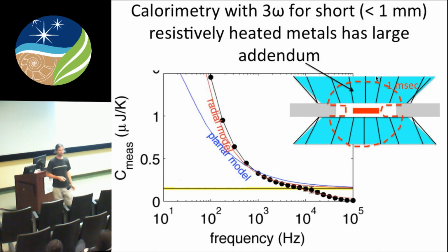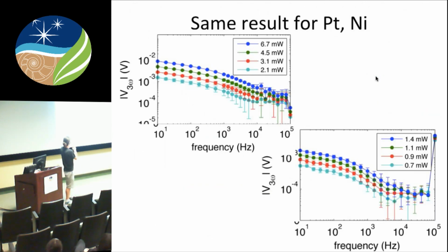I am, kind of. But I'm measuring at 4 orders of magnitude lower voltages than my input voltage, so it's pushing to the limit of these electronics. They're pretty harmonically pure. When I use a reference, I get even better signal to noise, but there's still some spurious signal that's not symmetric. So I can understand this data qualitatively, and it has a potential future, but this isn't the direction I headed, because I was too disappointed that I couldn't make robust quantitative measures of heat capacity of metals, and I had a better idea.